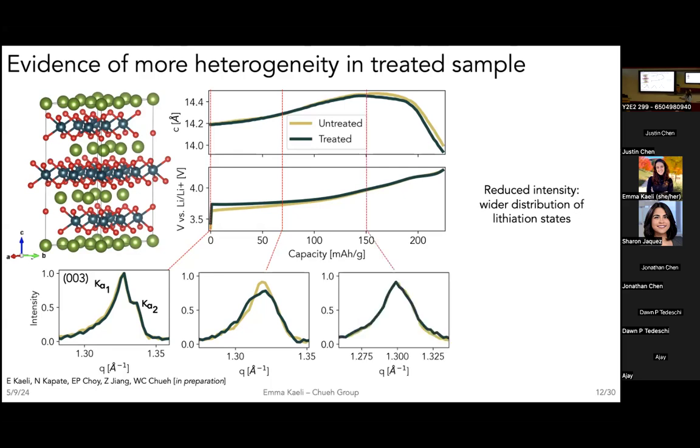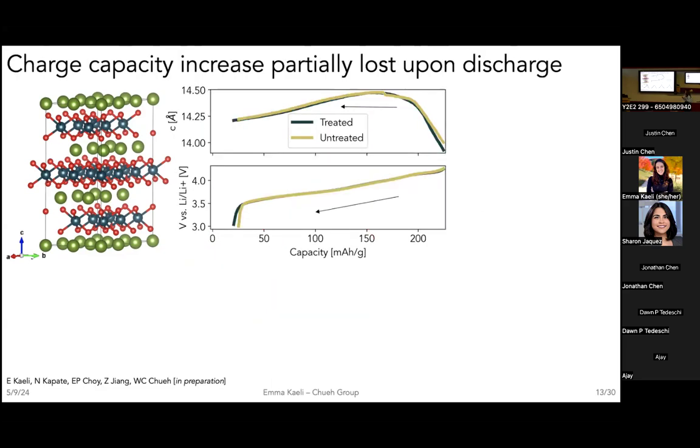As we continue charging, if we want to make sure we're seeing all the behavior we expect, it does become unimodal at the top of charge. And this is a result of us overcoming some of that high resistance due to the high driving force on the more resistant particles. And then finally, at top of charge, we start to see a splitting again, actually, as a result of some of those faster, kinetically improved particles, again, because we're in a high resistance region. So we should see different behavior on discharge if this is really impacting our discharge behavior.